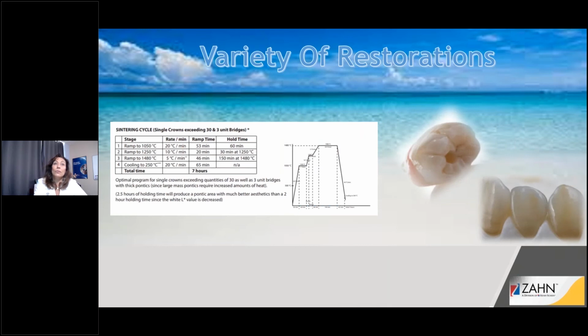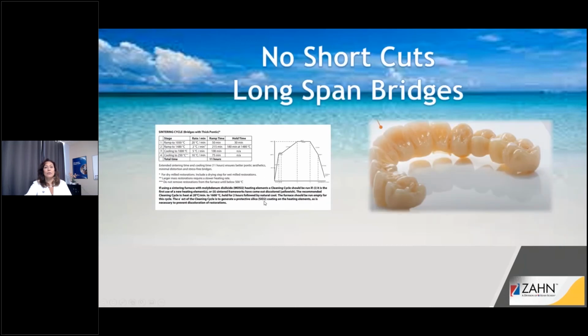All right. If you are doing a variety of restorations, say bridges, screw-retained crowns over abutments, crowns over abutments, anything, long span bridge, thick pontics, you really do have to use the 7-hour program. If you use the 4-hour program, the restorations will still look fine, but you aren't going to get the intensity of chroma that you're looking for. Those units are not going to absorb the amount of heat that they need during a shorter cycle. So the 7-hour program would be more appropriate. And again, on this one, it does say go to 1480 as your high temp. Again, you're going to be deciding what your high temp is based on your preferences.